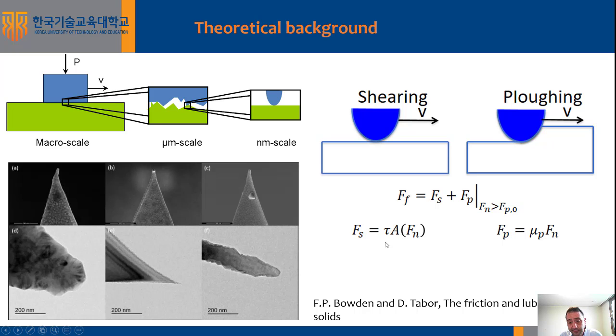So here we make the assumption that the shear strength is load independent, while the contact area A follows usually either the Hertzian model for elastic contacts or its modification by considering some adhesive forces. In this case, we would rather apply the Johnson-Kendall-Roberts model.